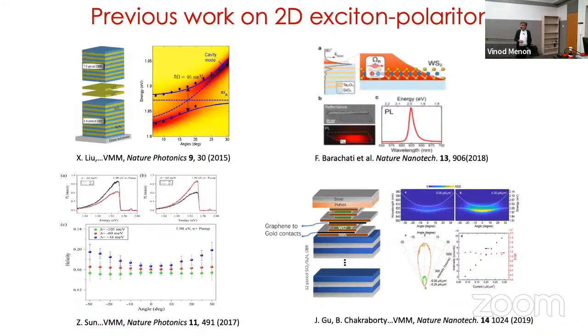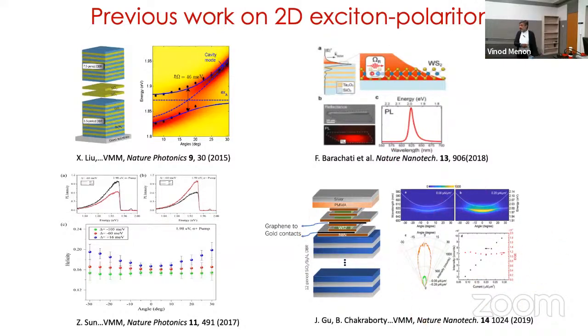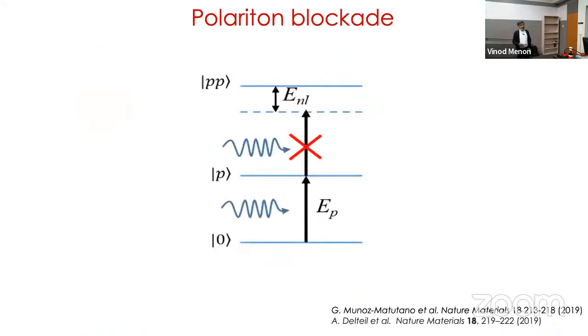Back in 2014 when we started working with 2D materials, the first experiment was to see if we could strongly couple to these excitons — we put the 2D material between two mirrors and observed the anti-crossing from strong coupling. We also showed that these polaritons preserve valley properties, that polaritons propagate long distances even with disorder, and finally that we can electrically drive polaritons by injecting carriers into the TMD layer which recombines and strongly couples to the polariton system.